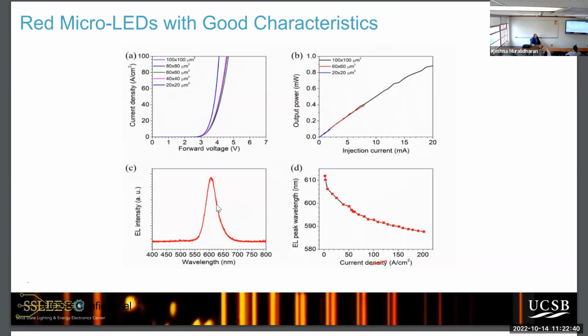All other characteristics are good. The wavelength looks good in the red. The voltage is good. So 3 volts means it's easy to drive, from your iPhone, there's a 5 volt power source, so easy to drive, and power's good. But the wavelength shift is a little bit big. So we'd like to fix that wavelength at a fixed current and then probably do pulse width modulation around here.